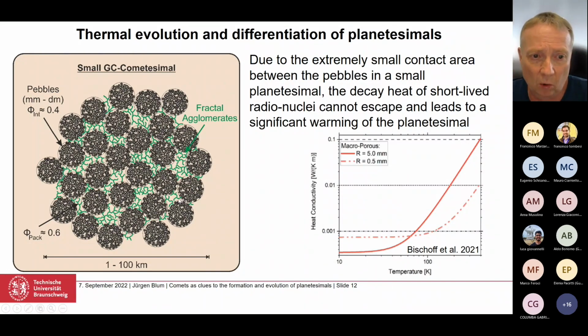and it turns out it's heavily temperature dependent. If the temperature is low and radiative energy transfer is completely unimportant, then the heat can only be transmitted through the contacts between the pebbles. And you can imagine this contact area is very, very small. So we have conductivities in watt per meter and Kelvin on the order of less than 10 to the minus 3, which is a factor of 1,000 or even 10,000 less than for normal ordinary materials. And that means at low temperatures, the heat conductivity is basically zero.